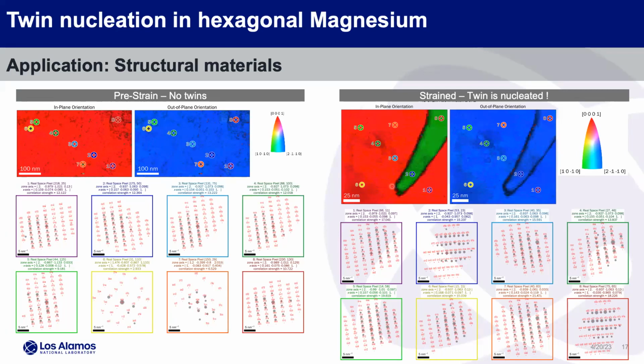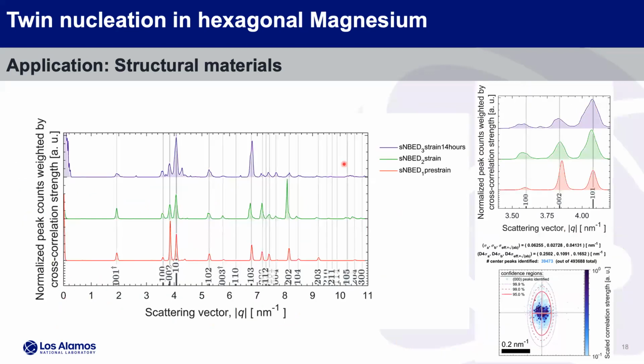When we looked at the strain state, because we're doing diffraction analysis, we can compare the strain state in the regular material and the strained material, and then look at it after we leave it for 14 hours. So you can see there's nothing there. You strain it, it's strained, and it relaxes a little bit and gets much messier if you leave it for 14 hours. This is an analysis of the entire diffraction pattern for the whole sample window that we're looking at.